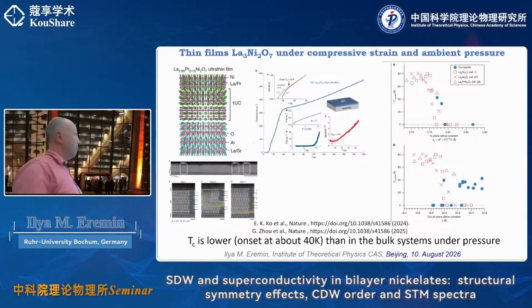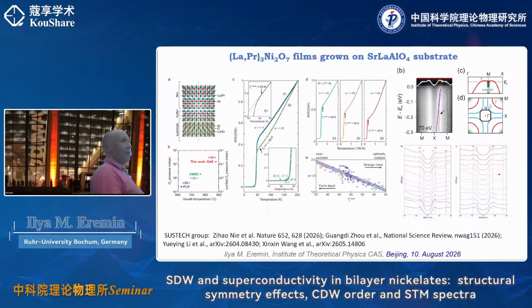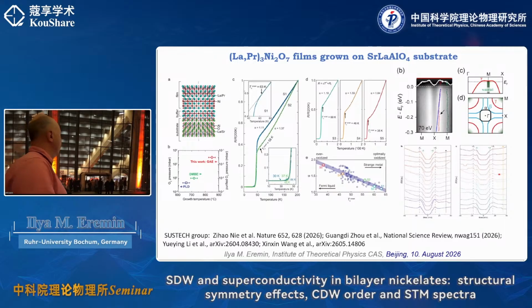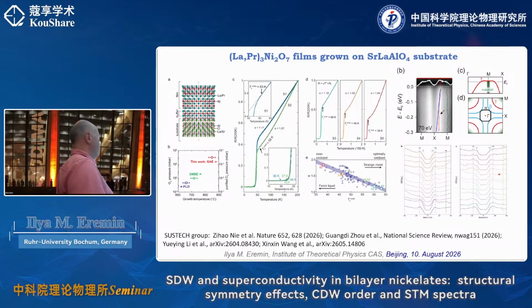Let me, however, mention that the most recent progress on the symmetry of the superconducting gap, on measuring the superconducting gaps, also comes from the SUSTech group, which managed to grow very nice films, and the highest superconducting onset temperature is 63 K, where there has been very convincing evidence and a series of papers showing a very nice transition.